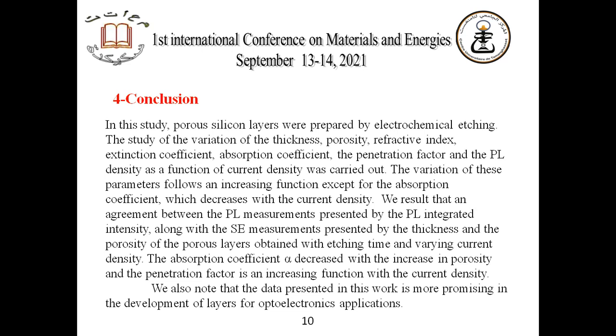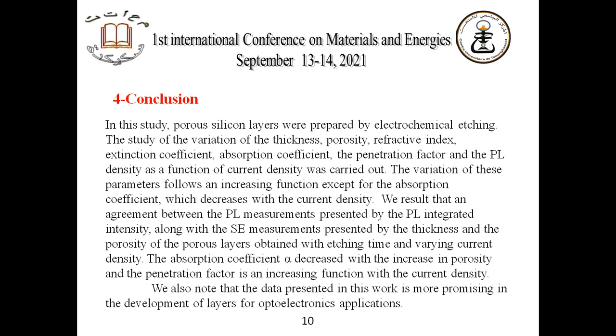which results in an agreement between the PL measurement presented by the integrated PL intensity, along with the spectroscopic ellipsometry measurement presented by the thickness and the porosity of the porous layers obtained with etching time and varying current density. The absorption coefficient decreases with the increase in porosity, and the penetration factor is an increasing function with the current density. We also note that the data presented in this work is promising in the development of layers for optoelectronics application.